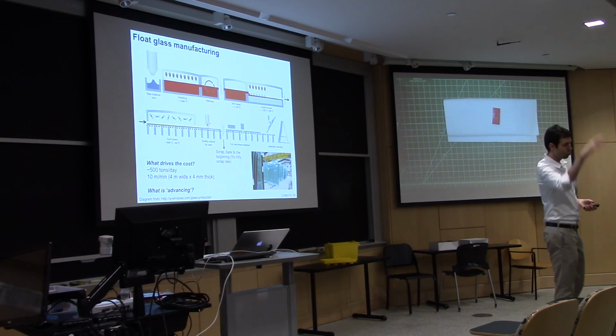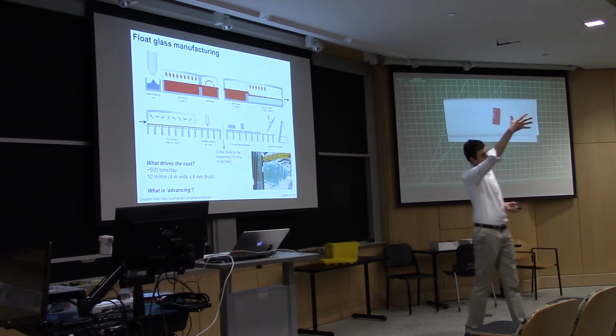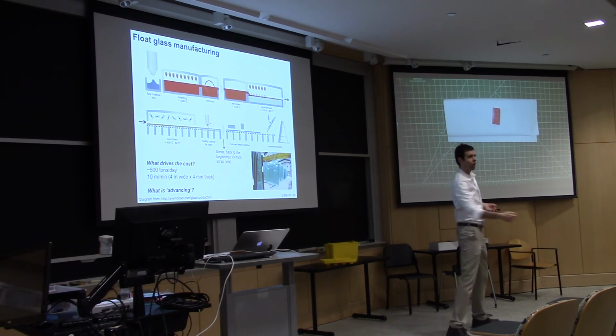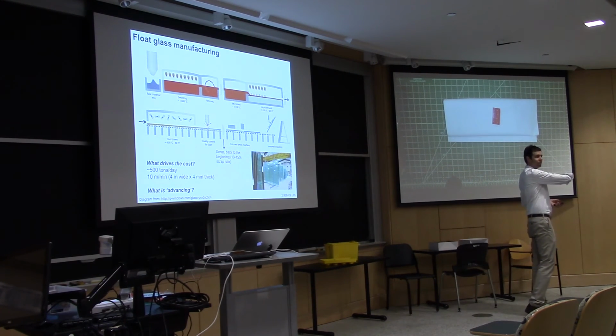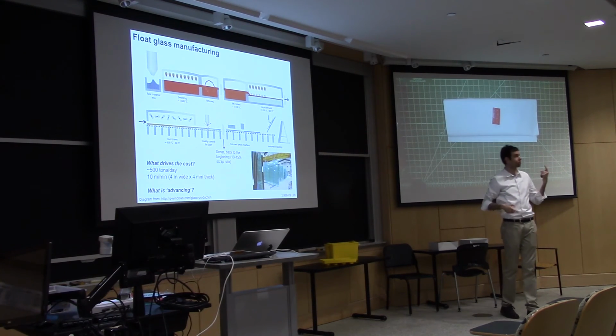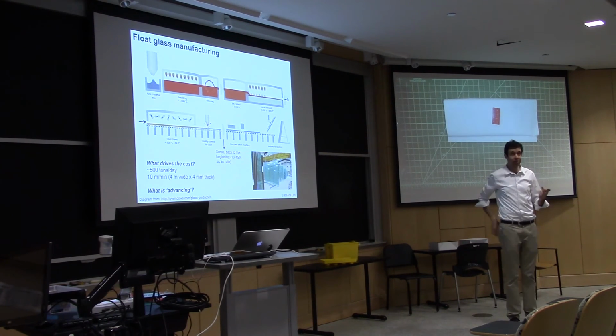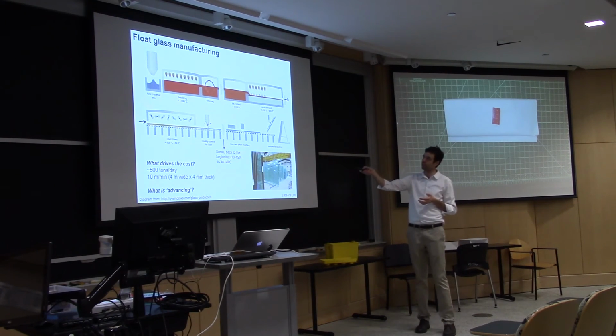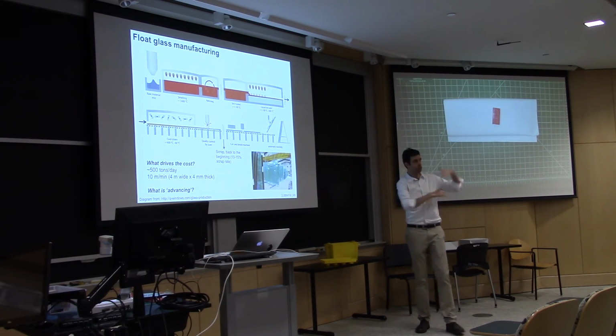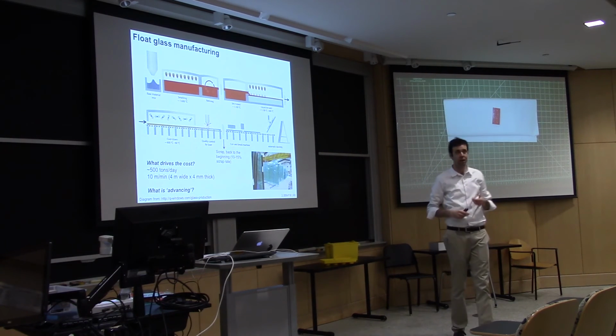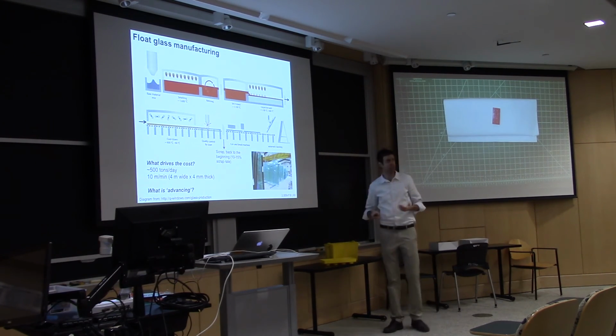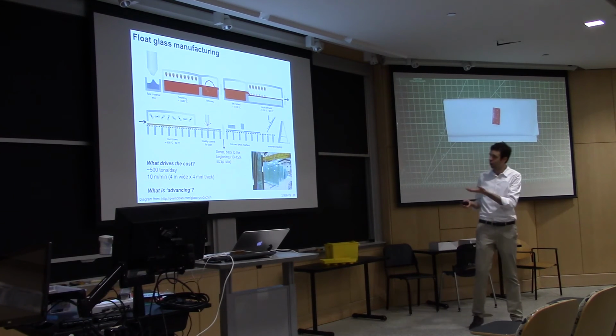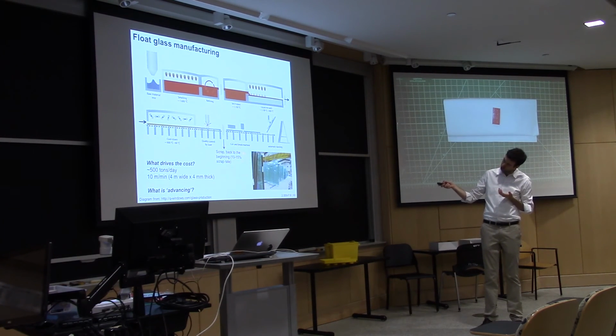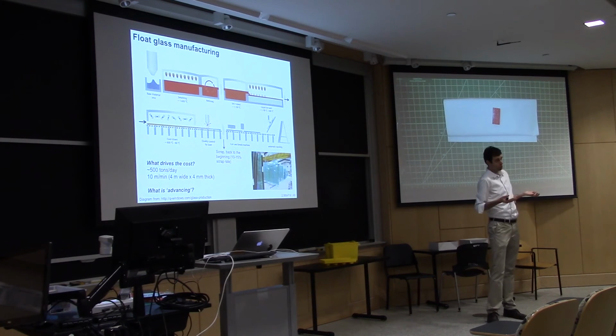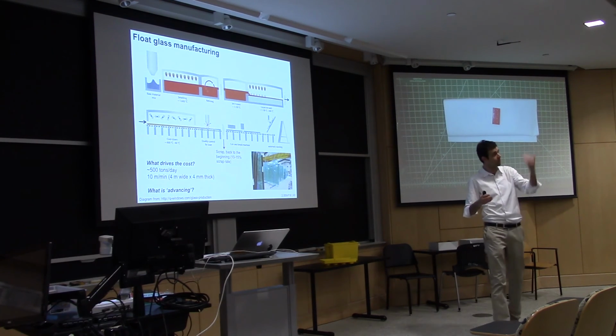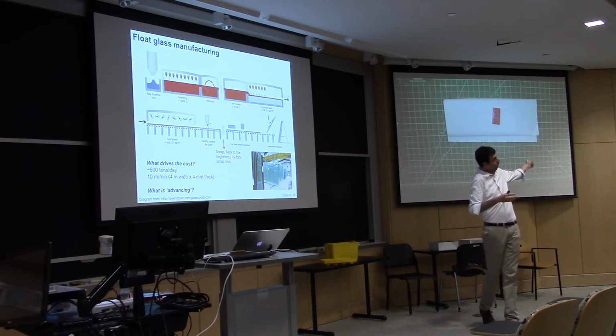And if it didn't meet the spec, a robot would come in, pick it up, turn it 90 degrees, and drop it down in a trench. And it went all the way to the back of the line and got mixed into the new product. And this did 2 things. One, it was like in situ recycling. Second, they said it kept the feedstock more uniform because the process changes if they have significant variations in the input feedstock. And third, it was like a different philosophy on quality. Clearly they couldn't afford that if the scrap fraction was huge, but 10 to 15% was okay. So they could allow a certain level of defects because they were able to send the product back to the beginning.